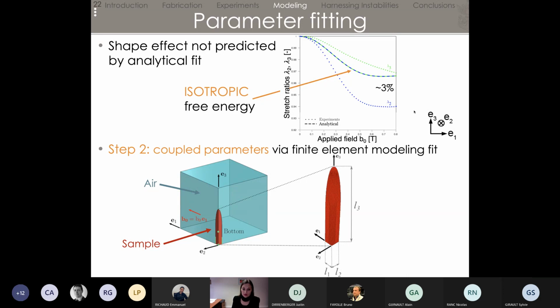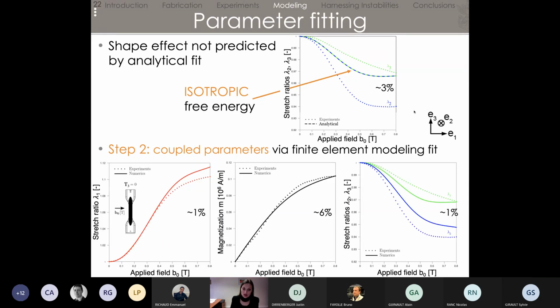When you're dealing with magnetorheological elastomers, you also have to mesh all the air around your sample as well. So it's already something that costs a lot in terms of computation. And then you need to proceed to parameter identification via finite element, which is also extremely costly. It doesn't give you really nice results, as you see on the left: we identify with 1% error, and 6% error on the magnetic curve. And finally, we do a little bit better when we are plotting the 2 transverse directions that do not behave the same. On top of that, because we're trying to find multiple parameters at a time, there's nothing that tells us that we actually found the absolute minimum in the optimization or identification problem. So this is really not something that's easy and clean in terms of material parameter identification for these materials.